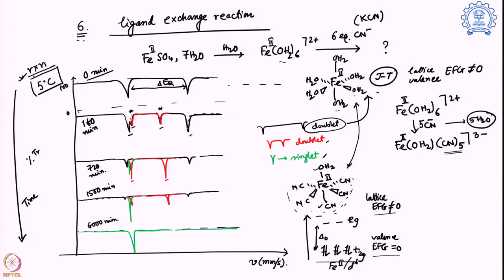And that is why, between these two, this system over here will shrink down on its quadrupolar splitting. So are we saying that this is the lower quadrupolar splitting that we are seeing? That is because of this particular sample over there, which is giving me this doublet. There is a possibility of that, and that is what is actually happening: the cyanides are making the system a low spin system. The quadrupolar splitting is shrinking down because there is no valence contribution from there.